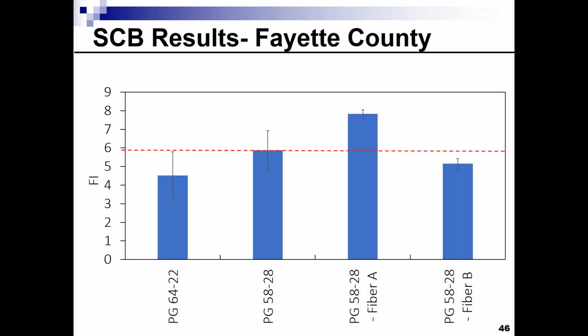For Fayette County, what we have seen is that the flexibility index was very consistent with the CTI results. Fiber A had a better flexibility index and cracking resistance as compared to the unreinforced mix, PG58-28. Fiber B seems to have slightly lower, but again, it's within that statistical difference. So I would say that they were similar.